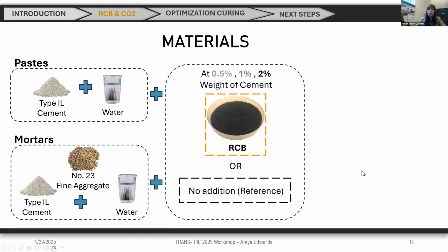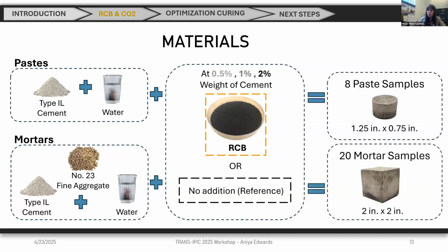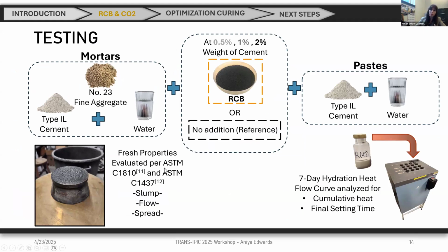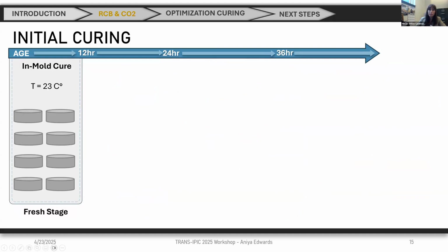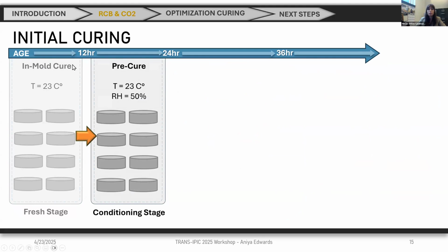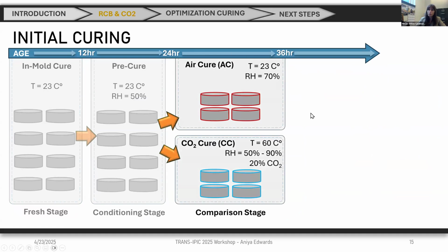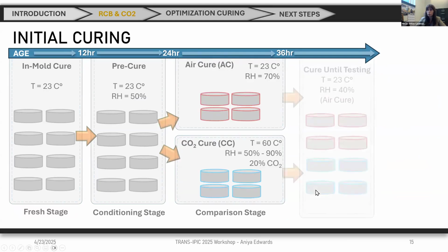Then what we did in the first studies that we were focusing on is making pastes and mortars with different percentages of recovered carbon black and no carbon black too. And then we did several tests. So we did the fresh properties for sure, and then we also did ICP. But with the hardened properties, which are the ones that I will mention right now, what we did was just first keep the samples in the molds, do some pre-curing, and then half of the samples of each mixture will be air cured, while the other half will be CO2 cured.